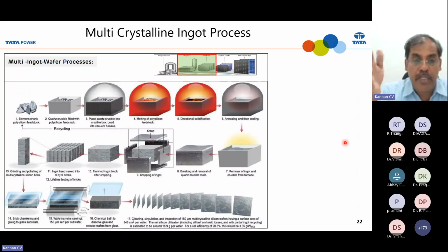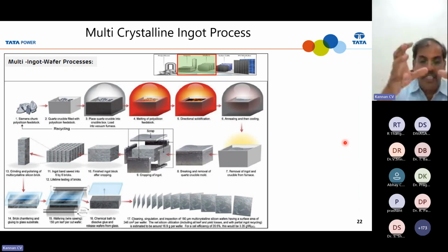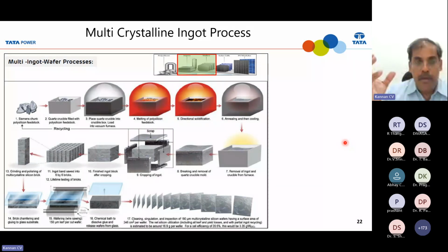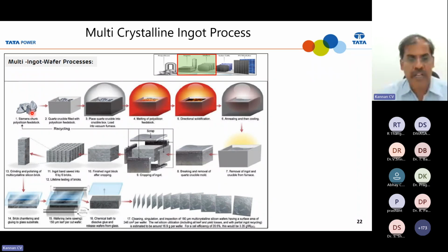So directional solidification means there is no pulling process. So there is a crucible, and the high purity polysilicon. This is the high purity polysilicon. The purity of silicon will be 9N, 10N. When I talk about N, it means 99.9999, that much of purity. Ultimately, we need 100% purity, but you cannot achieve 100%. So the previous low quality silicon will be 99.5% purity. So the 99.5% purity will be converted into 9N or 10N purity high purity polysilicon through chemical processes.